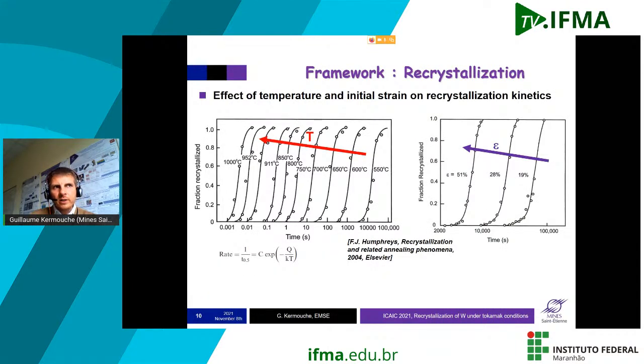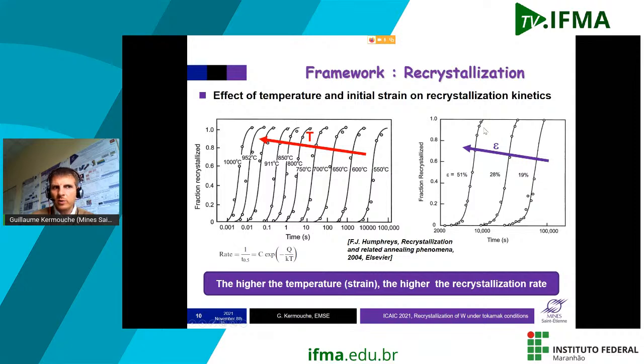You can see here the effect of temperature and strain on recrystallization. If you increase the temperature, as I said before, you increase the recrystallization rates. And if you increase the strain in the material, the stored energy in the material, so it depends on the thermomechanical process you use to finally get the tungsten material, you also increase the recrystallization rates. So the higher the temperature or the strain, the higher the recrystallization rate.